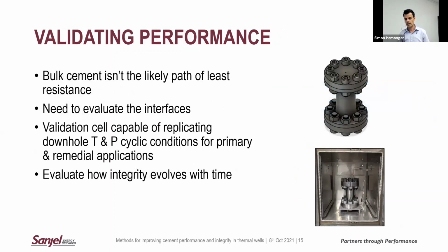So finally, validating performance. I think it's interesting to talk about yielding not impacting the bulk properties or bulk permeability. But realistically, I'm not sure if the bulk cement is the path of least resistance when it comes to loss of integrity. I think the interfaces are what really need to be looked at, especially the cement casing interface. That's not a strong interface. That's typically a mechanical interaction predominantly, and really one of the main ways that failure mechanisms can occur.